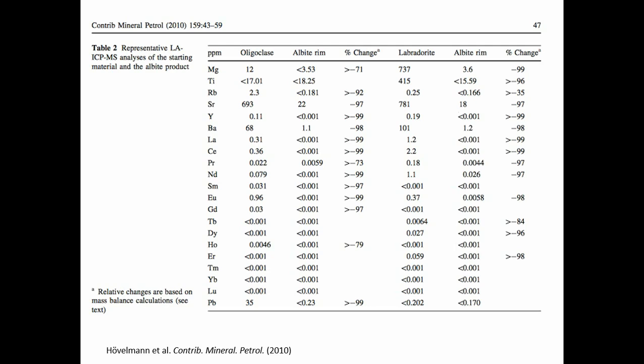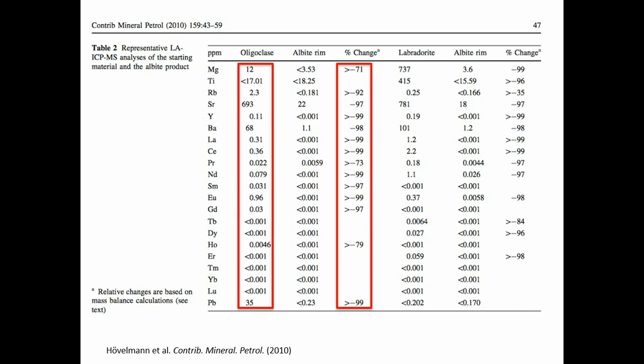And so we've done a lot more work on this, chemical analyses. We can show that it's not just forming sodium albite, the sodium plagioclase. I don't like showing lots of numbers, but if you look at the left-hand column, you can see that a lot of elements were present in the original oligoclase and the labradorite. That was from the natural samples. After the experiment in the oligoclase, you can see the albite. We have almost lost all of those elements.